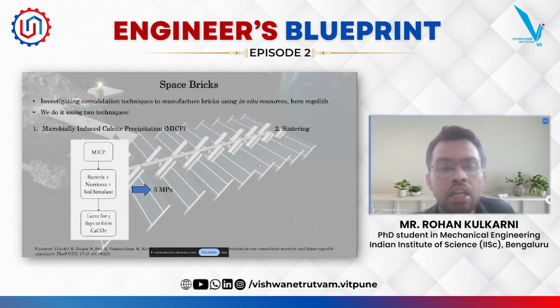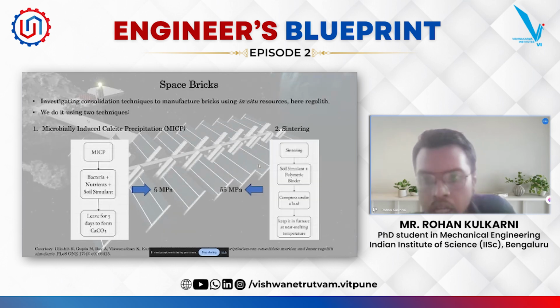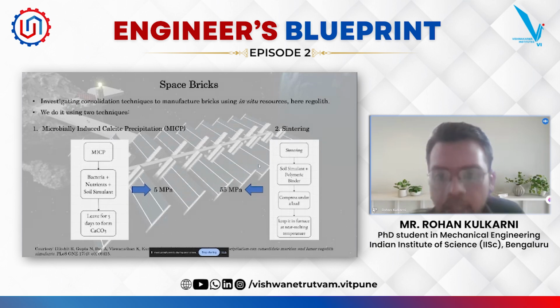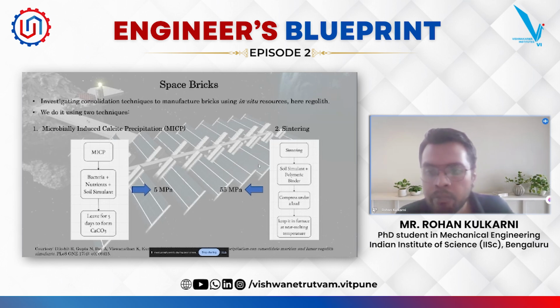These are the bricks that we use on Earth. So these bricks give us a strength around 20 to 30 megapascals. Another technique is called sintering. In sintering, we have a soil simulant, we use some polymeric binder, then we compress this mixture under a load, and then we keep it in a furnace at near melting temperature. We have performed this, and we have reached a strength of 55 megapascals using the lunar soil simulants.